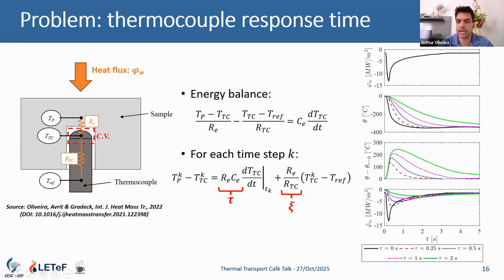If we simulate the thermocouple response time - something everybody knows, it's not new - if I have a prescribed heat flux in my simulation that I want to estimate as my reference, depending on the thermocouple response time, I'm going to have different temperature profile responses. The black line regards the perfect thermocouple, no response time. As the response time increases, the thermal response is damped, and we can lose the fast transients of the process.